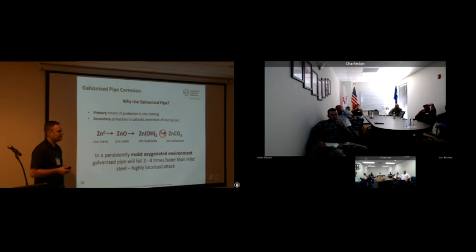The problem is, where that little arrow crossed out is, we don't stay in this state. If you take the zinc carbonate, a galvanized piece of metal, and you keep it consistently moist, it will revert back to zinc hydroxide. So anyone that's opened up their galvanized system, seen white fluffy material in there, that's the zinc that's actually coming off your pipe. That is the zinc hydroxide.